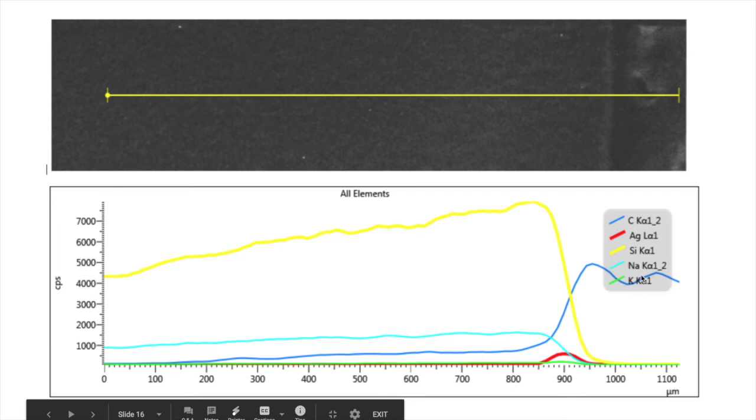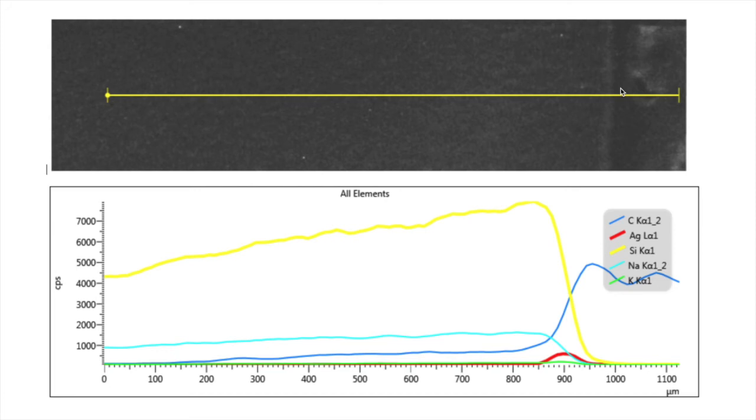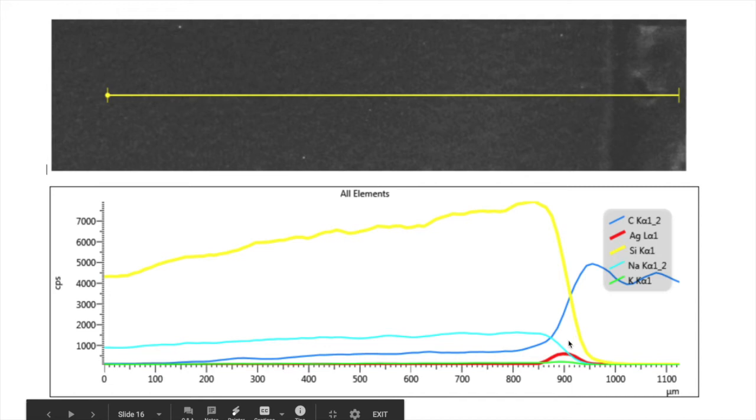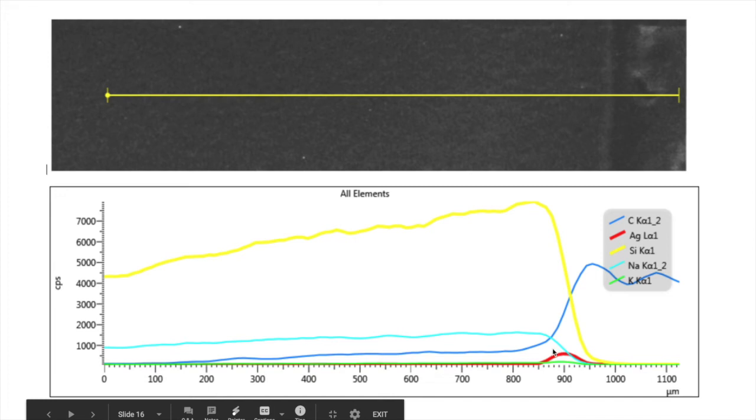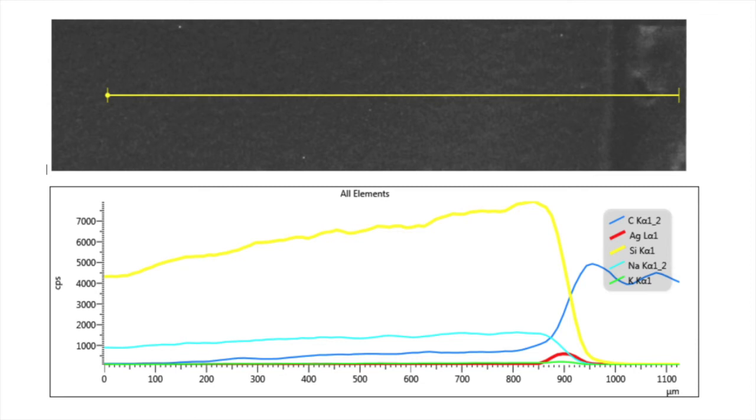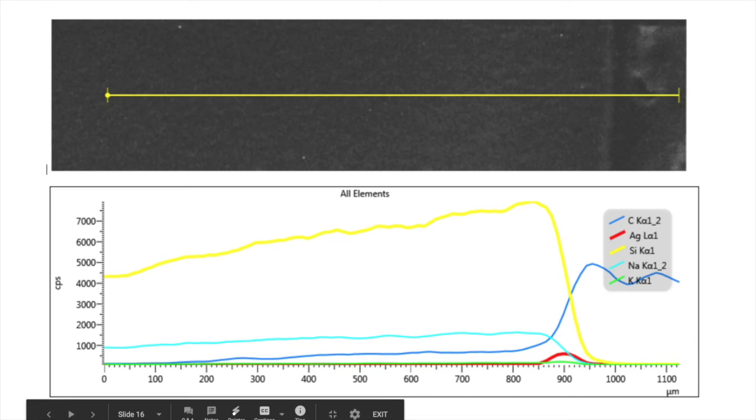And then carbon, which tends to be an impurity, it could be on the carbon tape that goes up at the surface. And then beyond that, we see sodium, potassium is very low. But then you also see a little spike down here for silver. So silver is basically right at the surface. And then the rest, it's a very low level. So basically, you only see silver right at the surface of the glass rod. And then the sodium actually goes down in that same region. So we see that there's an exchange, effectively, between sodium and the silver in the glass.